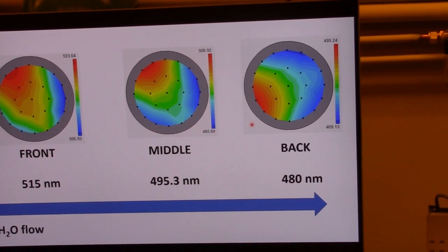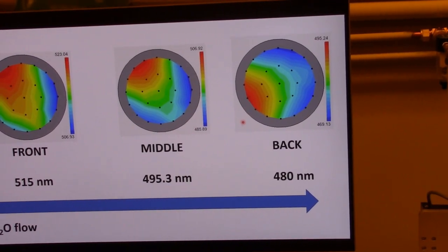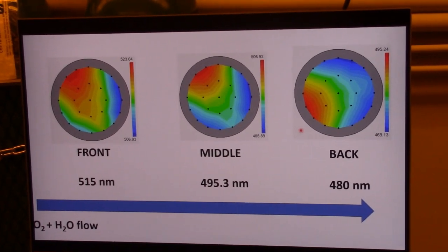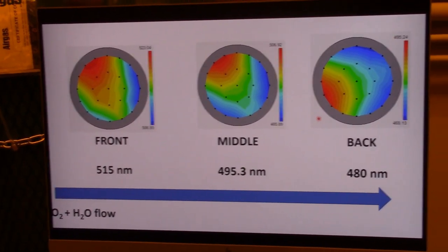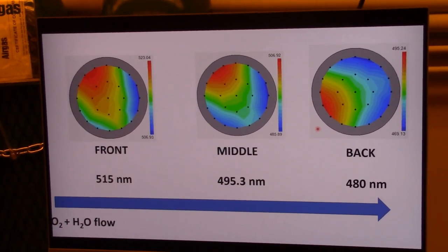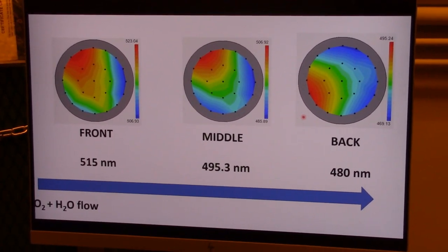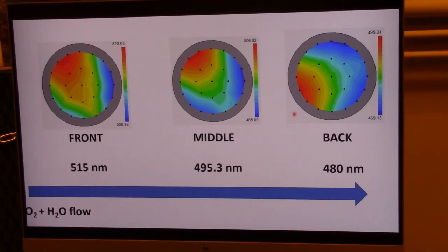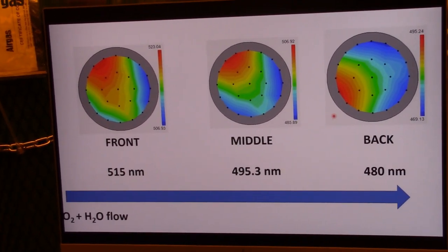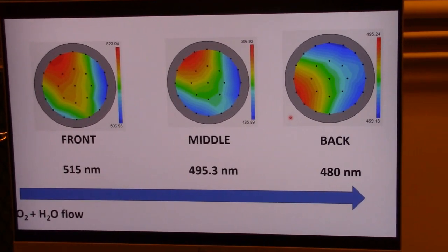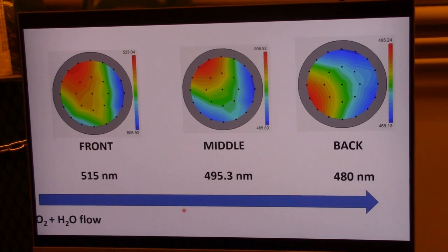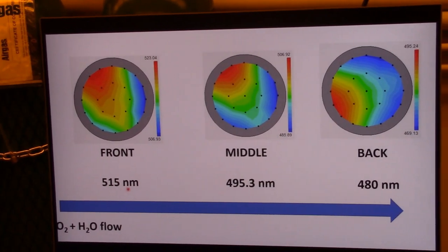It's important to make sure that you have a minimum thickness of around 450 nanometers for the pad oxide, so that it acts as an effective diffusion barrier later on when we do spin-on coating of spin-on P-glass and diffuse phosphorus through the rest of the wafer, where the pad oxide acts as a barrier in places where we don't want to dope the wafer. So we've been able to achieve above 450 nanometers, but there is a slight variation in the thickness that you see.